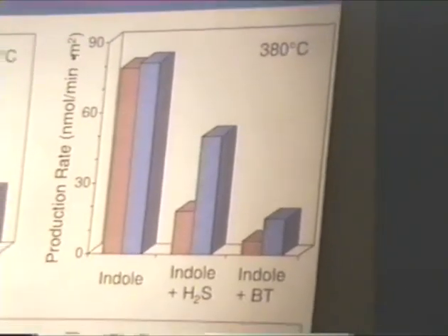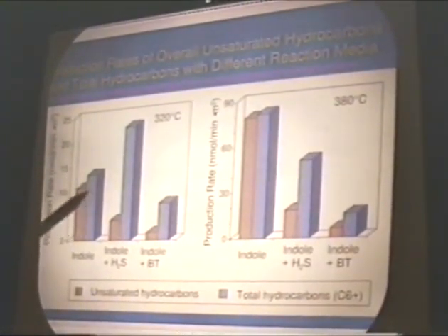Now, obviously, the saturation ratio of these hydrocarbons is important because we don't want to use up a lot of hydrogen unnecessarily saturating the hydrocarbons in the process of denitrogenation. So here we are comparing total hydrocarbons, C6, C7, C8 combined, and unsaturated hydrocarbons. You can look at them as the more desirable products. Again, if we look at only the indole case first, at two different temperatures, what we see is that unsaturated hydrocarbons pretty much make up almost all of the total hydrocarbons, meaning we don't have a whole lot of hydrogenation at